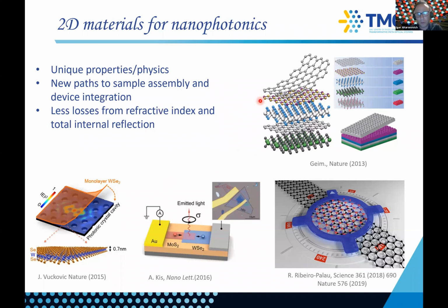So 2D materials are unique in this regard because you can make devices very easily. And this Lego style, this picture is quite old, but it's really powerful because you can really assemble devices and put them on cavities and put them on resonators, as was done by many groups. So here's one example where they put a monolayer on top of a cavity. And when you think about fabrication, it really saves you a lot of time. And of course, it has a plethora of interesting effects. So the superconductivity in graphene you've heard, probably, I'm sure, and some other twist-based effects, which are quite nice.